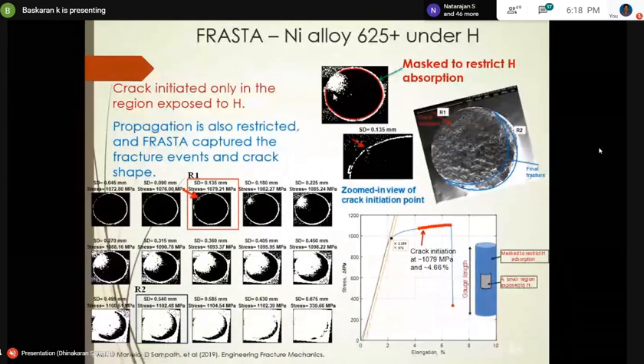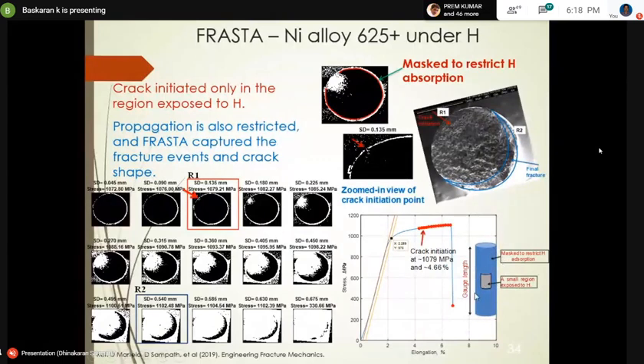And here we did a clever experiment using a different alloy. This is the gauge section of the specimen, and we just masked the entire gauge area except a small window which is exposed to hydrogen. And what we saw was the crack grew like a crescent. So yeah, this is very interesting, and that means the analysis we do is in fact showing the correct expected result.